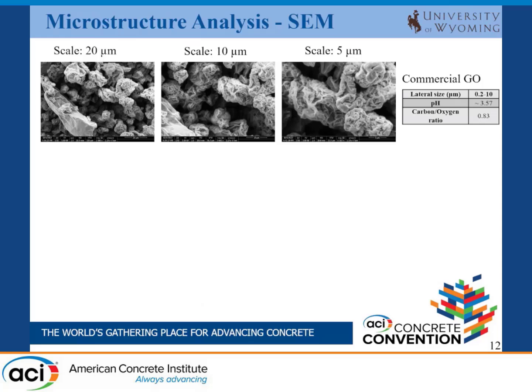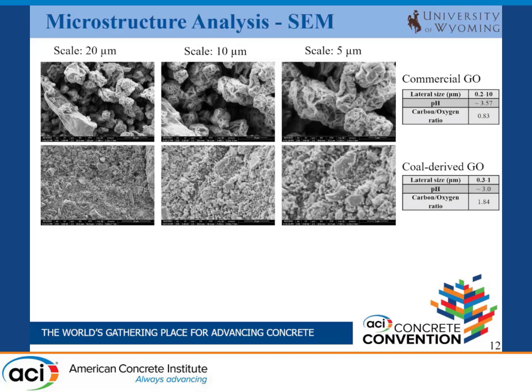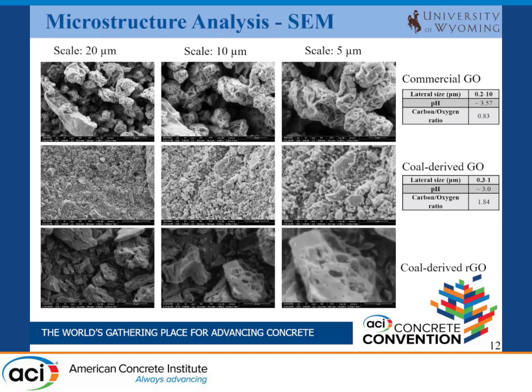So we did some microstructure analysis of different types of graphene oxide. In the commercial graphene oxide, under the 3 different scales from 20 to 5 micrometer scale, we found that the shape is more like a crumpled shape, and the lateral size is 0.2 to 10 micrometer, whereas the pH value is 3.57 and the carbon to oxygen ratio is 0.83. Whereas our graphene oxide, at the same 20 to 5 micrometer scale, has a lateral size of 0.3 to 1 micrometer, the pH is 3, and the carbon to oxygen ratio is 1.84. The same description applies to our reduced graphene oxide as well.